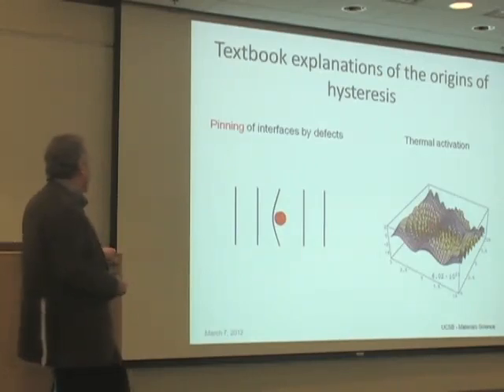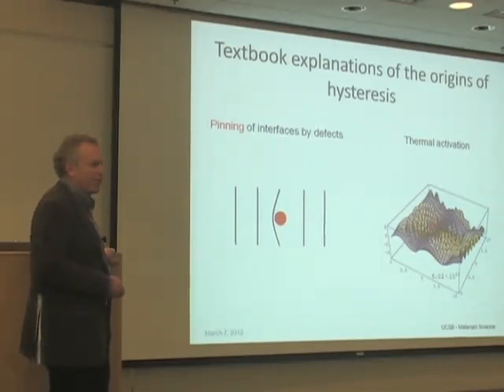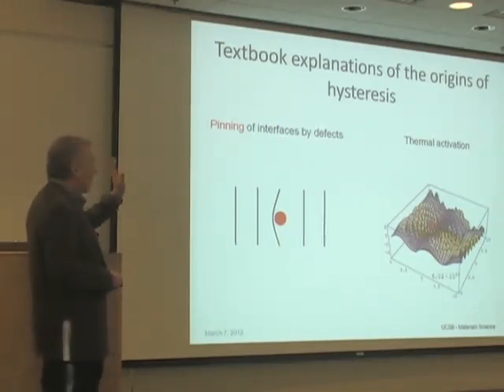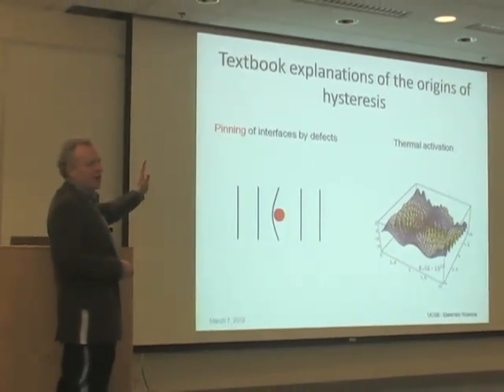People would usually say that it's the pinning of interfaces by defects that is responsible for hysteresis. And they would say this idea is borrowed a bit from magnetism. They say that there's an interface between the two phases. It eventually comes up against a defect, which is non-transforming. It requires an additional lowering of the free energy of the new phase to get this interface to snap through the defect, that is, an increase of the driving force to snap through the defect.